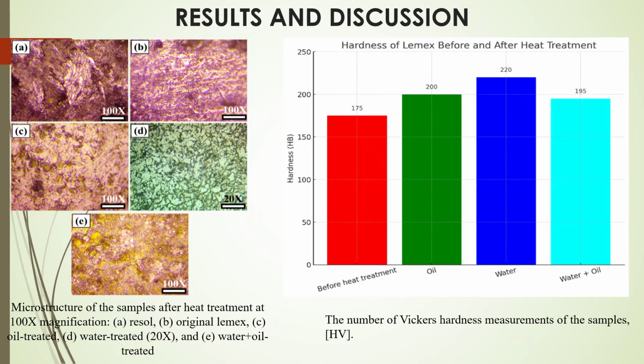In this section, we present microstructural changes and hardness measurements of the samples after heat treatment. On the left, you can see microstructures at high magnification. The images compare the resol material, original Lemex, and the Lemex after oil treatment, the water treatment, and the combined water oil treatment. After heat treatment, the grains become much finer and more compact, indicating improved mechanical properties.